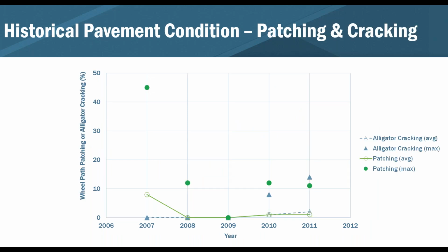And then finally, looking at patching and cracking, this one gets a little bit more messy. The patching are the circles, and the alligator cracking are the triangles. Again, the marker filled with a color is the maximum value, and the dashed line and the solid green line are the average value. You can see that for the most part, the alligator cracking on average wasn't terribly bad, maybe getting up to a couple percent over the years, but certainly the maximum at one location in 2011 was above 10%, closer to maybe 12, 13%. Then for the patching, you can see quite a bit of patching happened in 2007. They went through and did some repairs, and that drops and fluctuates a little bit more, depending on what they did.